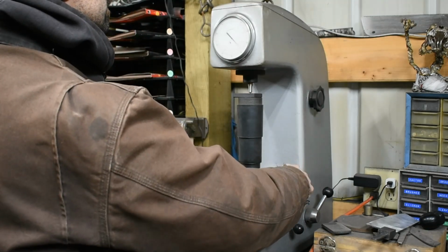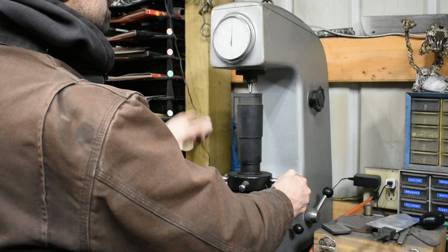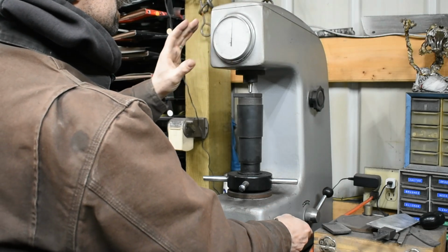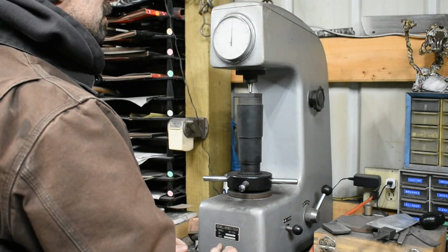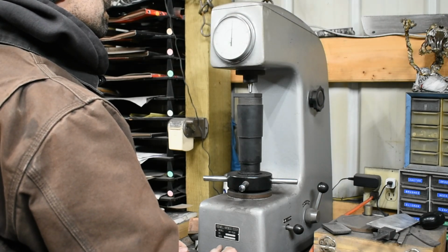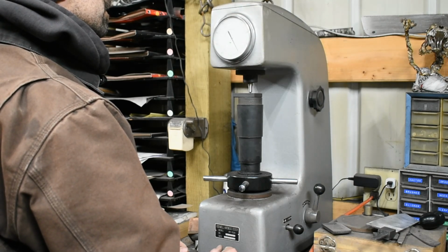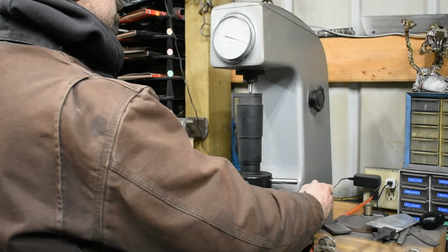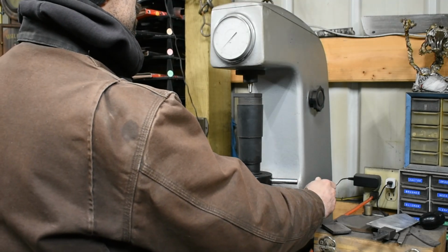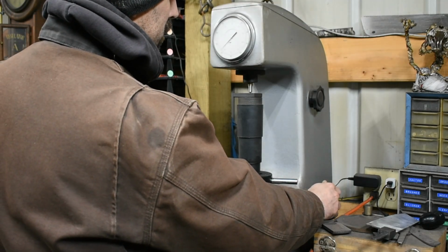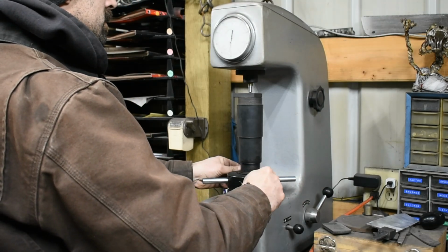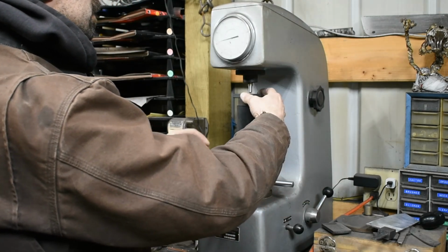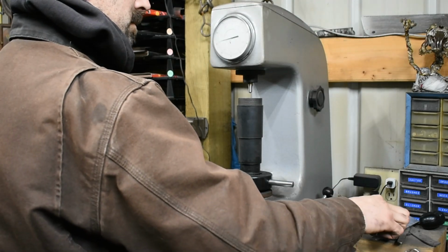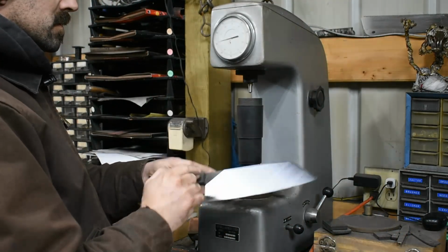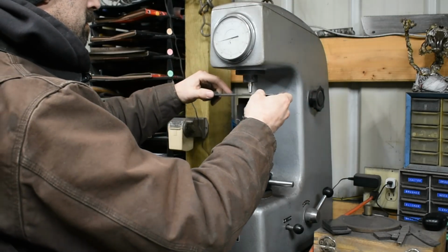With that done, over at the Rockwell machine here, I perform a few of these tests on the calibrating block first, just to make sure the machine is in trim, testing accurately enough, and if not, how far off it is. The machine was testing a little bit hard right now, which is common if it's a little cold in the shop. The damping oil gets more viscous, so I took that into account. It was testing almost 63 when it should be reading 62.1, so I adjusted all of my average test results down a bit accordingly.